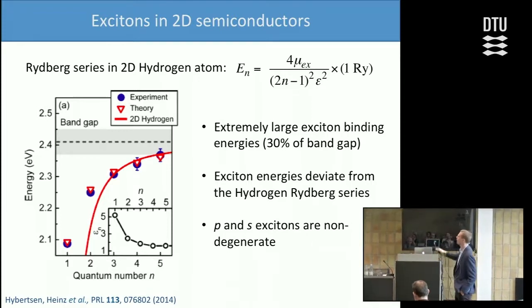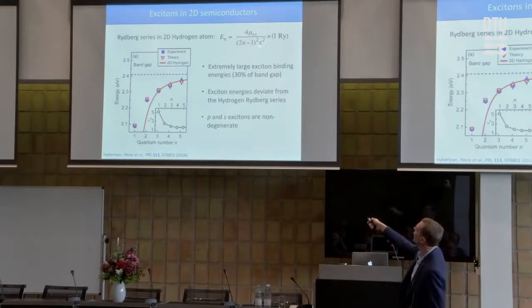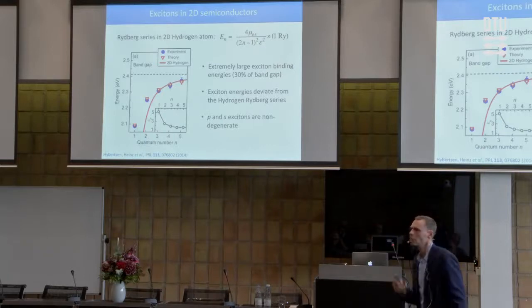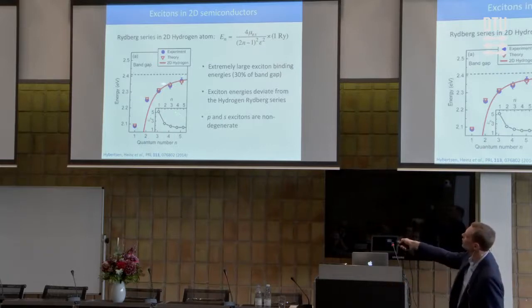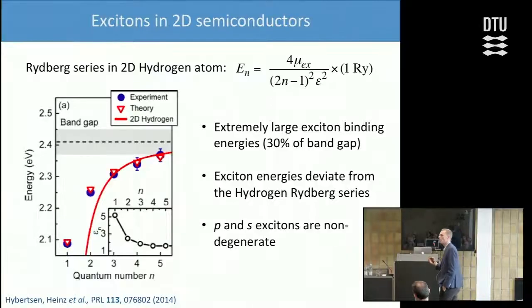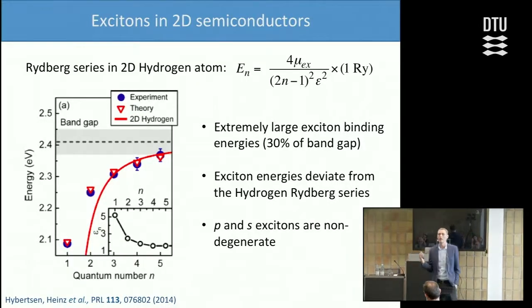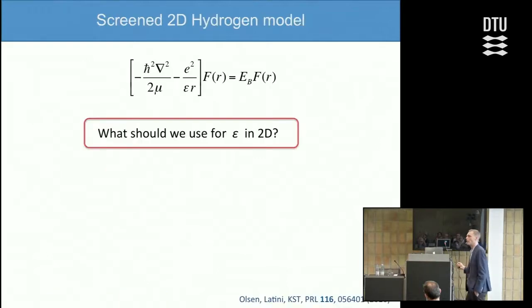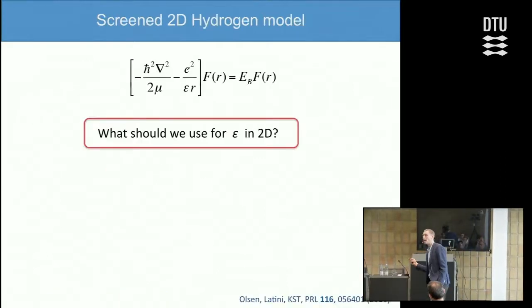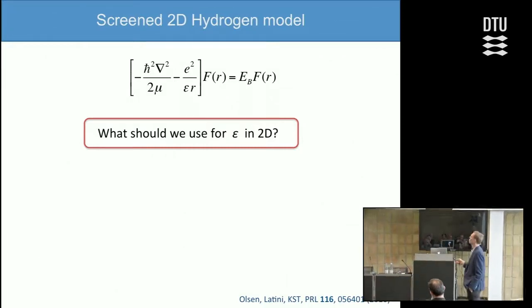So what they did in this paper to explain this was use the standard expression for the energies of a hydrogen atom, but with epsilons, dielectric constants, that were state dependent. By doing that, they could fit the experiments very well. Of course, it's not very satisfactory to fit these values to experiments, so we asked ourselves, can we calculate those ab initio, without any fitting parameters?